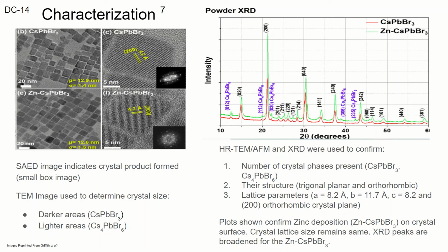As an interesting aside, the XRD shows a comparison between the red line, which is a spectrum of a perovskite crystal by itself, and the green line, which is a spectrum of a perovskite coated with a thin layer of zinc bromide. This packaging of the crystal with zinc bromide salt minimizes the crystal's contact with air to reduce Schottky defects, but it doesn't affect the crystal lattice structure or the photoelectronic properties of the crystals. So, this packaging idea is where current studies are going to address the air and moisture sensitivity problem of perovskites, which I think is really cool.